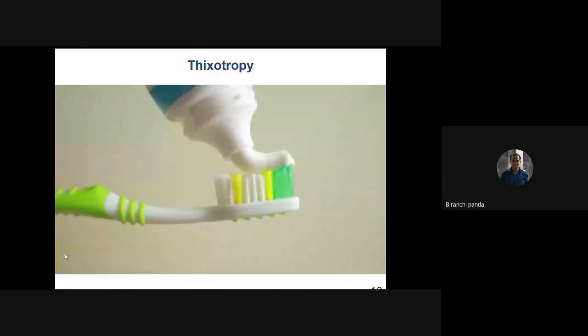So this toothpaste development is also a very R&D problem. It's not that simple. So they also try to develop a thixotropic material for this toothpaste application. We also want a similar property in our printing because we are pumping. So during pumping, we are applying some shear rate. With the shear rate, we expect the material to lose its viscosity so that it can be easily pumpable, easily extrudable. But once you deposit, once you remove the shear rate, it should remain in its own position without any deformation.